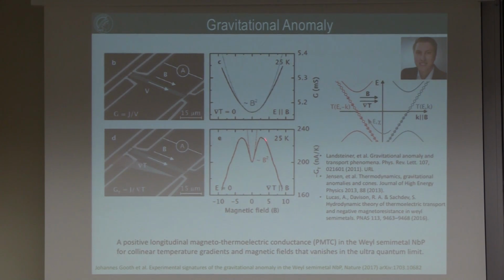So he did the measurement, and here's again the conductivity measurement. You see nicely the B square behavior. Now he applied the thermal gradient and measured the thermal conductivity, thermoelectric conductivity, and you see exactly what was predicted happened: it changed sign and then it goes nearly to zero. Okay, here the value is still high, but I think we can find now better crystals, better systems.